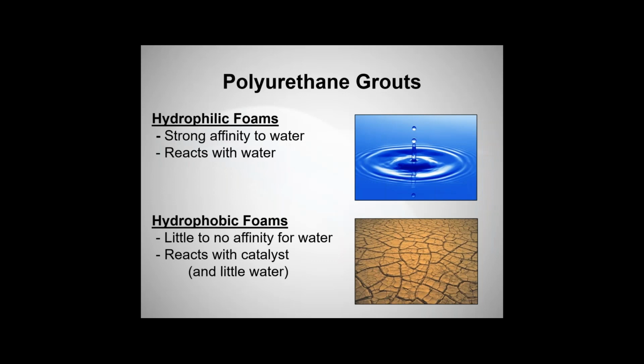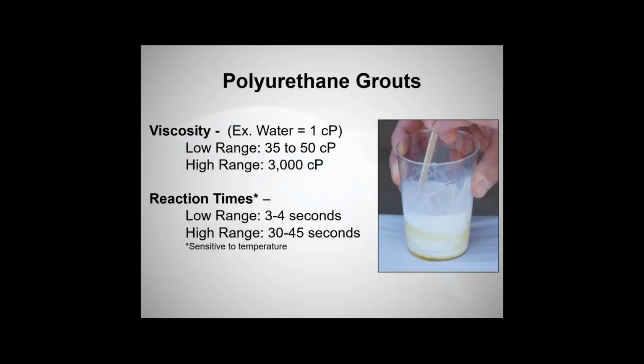So moving on to our solution grouts and the subfamily of polyurethane grouts. These consist of the hydrophilic foams. Hydrophilic foams have a strong affinity for water. They typically are single component and they react with water, whereas the hydrophobic foams have little or no affinity for water. They'll have a base resin with an accelerator, or also known as a catalyst, and a little bit of water can react to that reaction. And sometimes they're 1-to-1 mixed ratios as well, component A to component B.